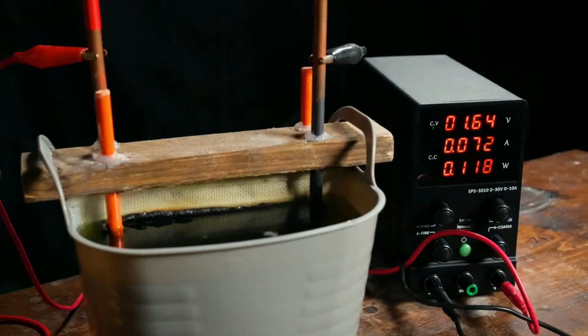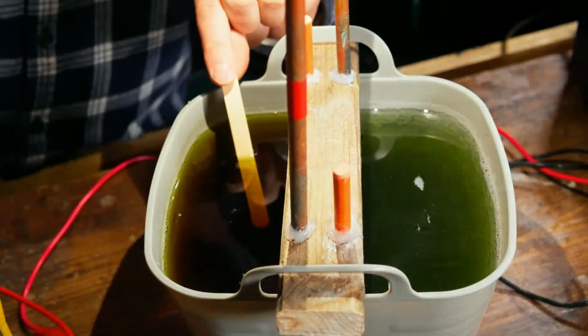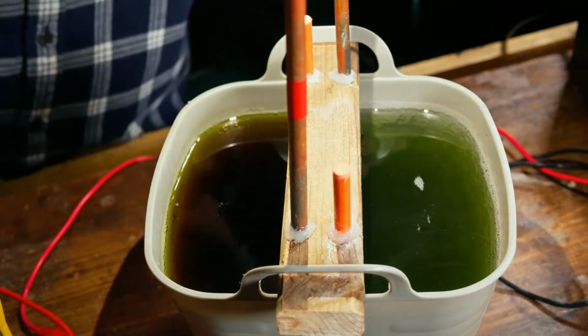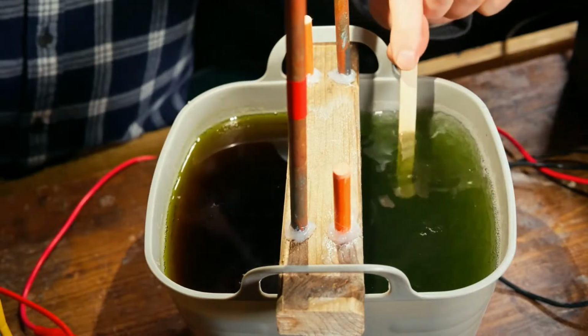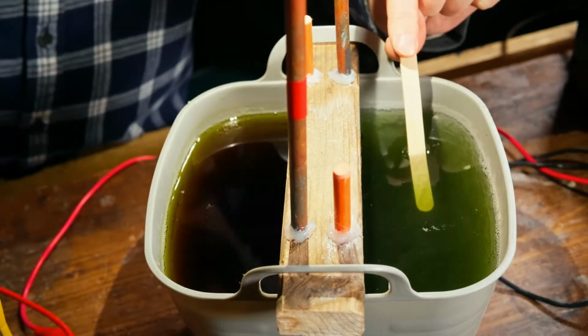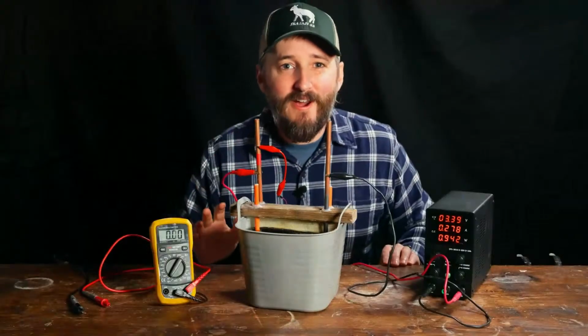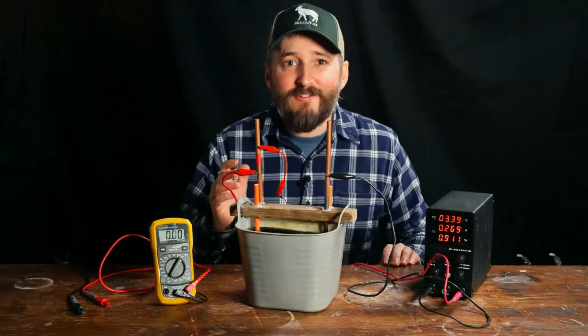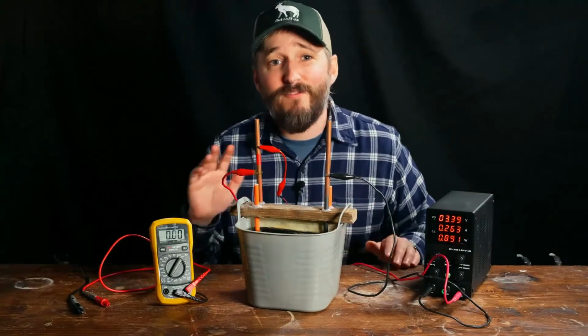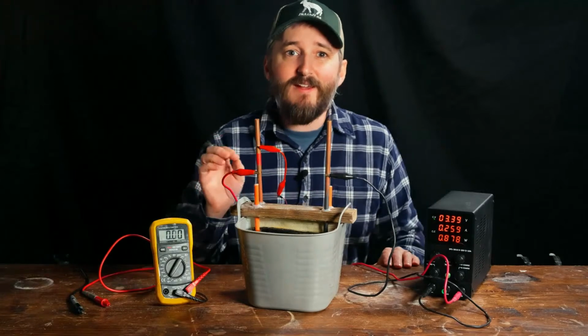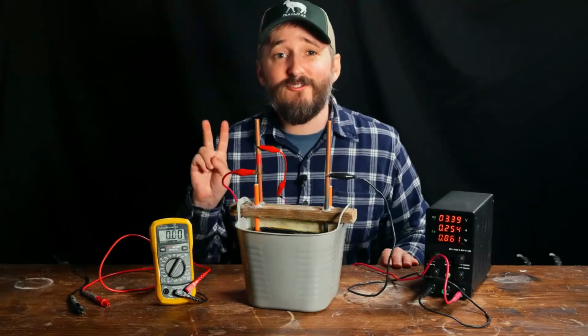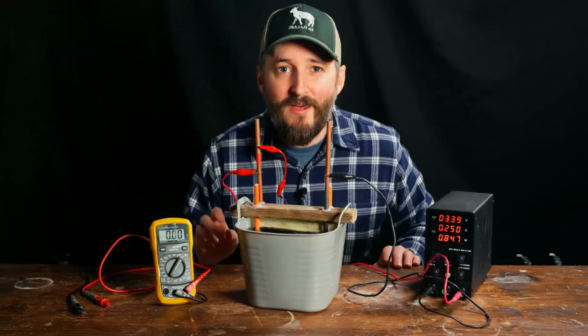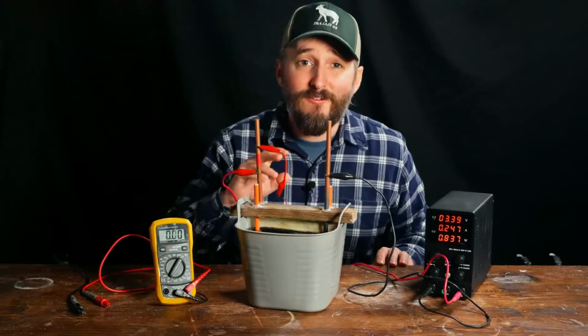After about 12 hours, the battery starts drawing less current, which indicates that it's charged. In an iron battery, you can also tell the state of charge just by looking at the color of the electrolyte. The positive side will be much darker than the other. This time we're not plating iron off as solid metal. The citric acid added to this solution prevents that from happening. Instead, we're splitting the iron sulfate into two different iron compounds, both of which remain fully dissolved.